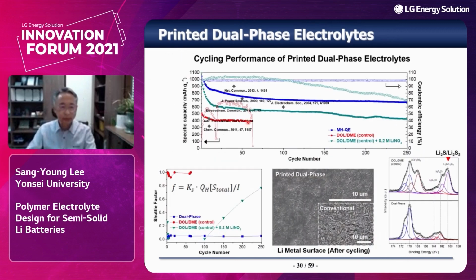So here is a very interesting result. Our case is the blue line. Our system shows decent cyclability, which is better than the conventional DOL/DME-based electrolyte, and also along with the lithium nitrate additive. When we use the additive, after a certain number of cycles, the shuttle factor starts to grow, which is a limitation of the additive-based approach. However, our approach is a kind of permanent one. And no change in the lithium metal surface was observed.